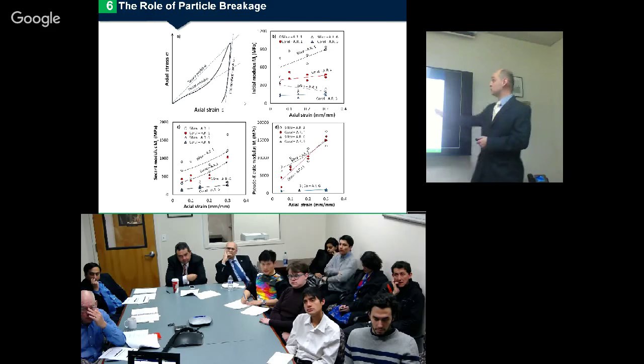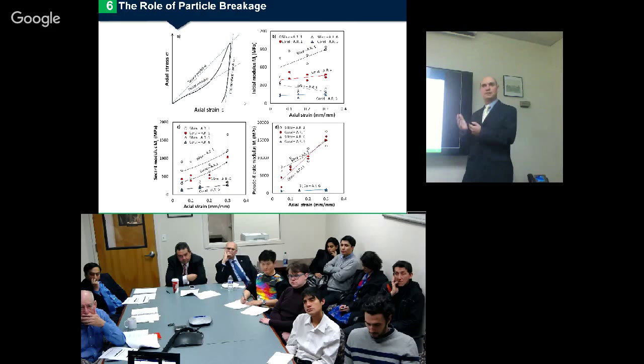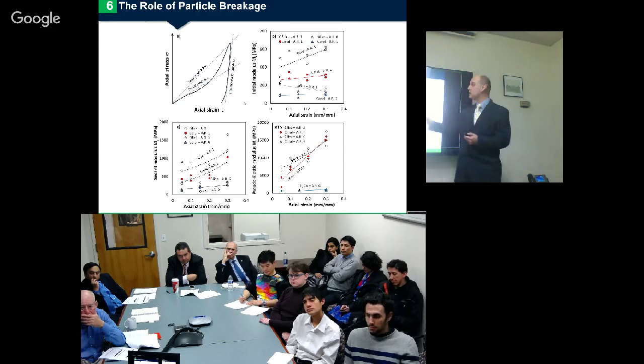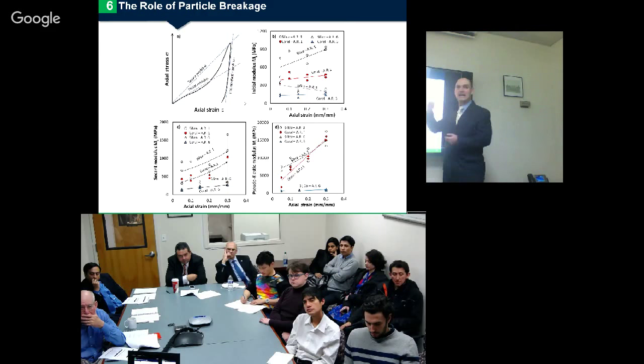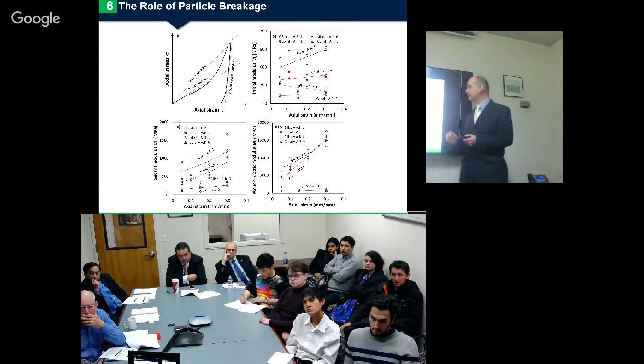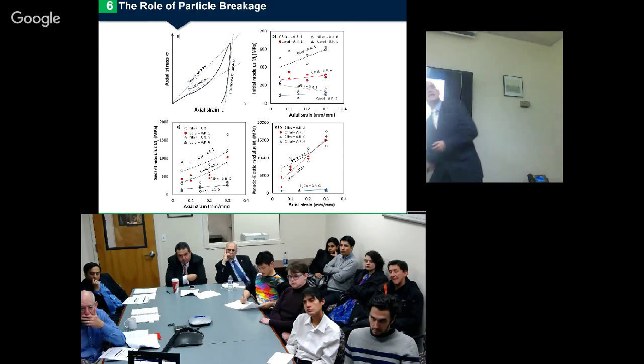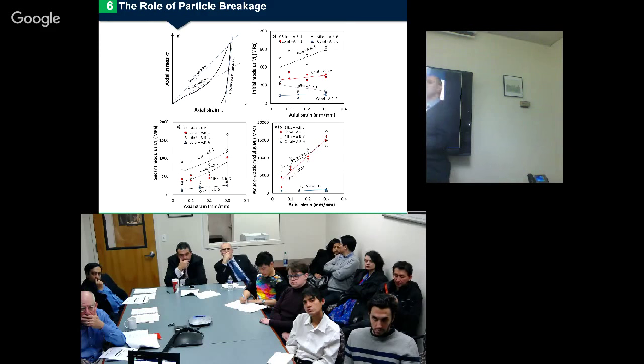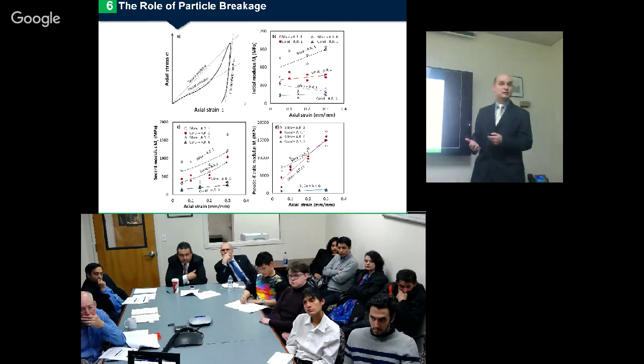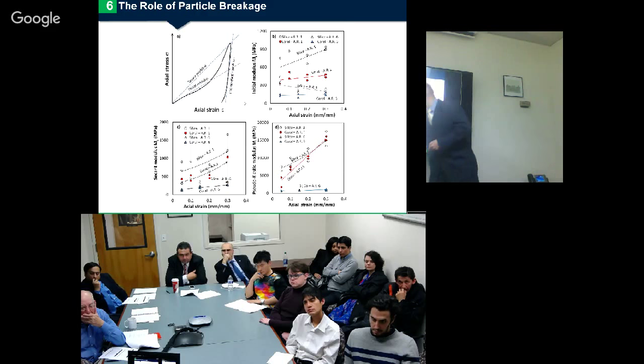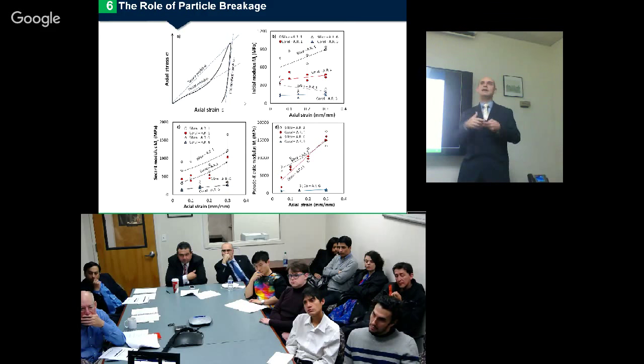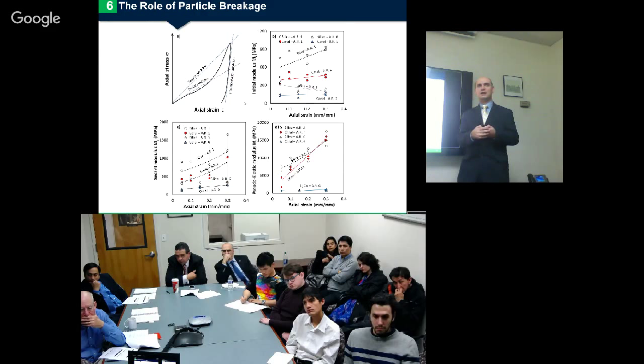So we were able to see something similar: behavior that is quite horizontal, and others that are slightly increasing due to the strain rate effect. The secant modulus obviously is going to change because we take measurements from here up to, if we arrested the experiment at 5%, from here to 10, from here to 30%. So these values are going to increase, unless we use large aspect ratios. Large aspect ratio means low axial stresses. With low axial stresses, the sample is not experiencing much change.